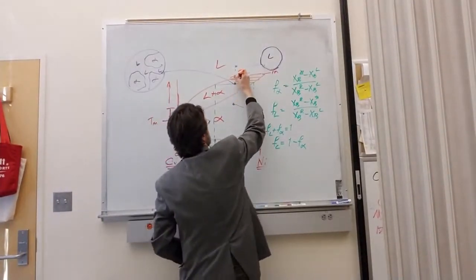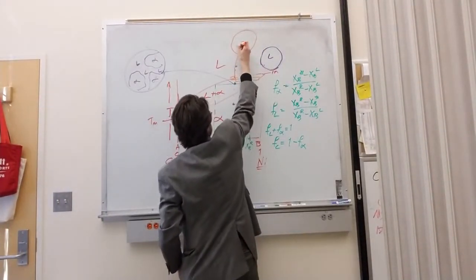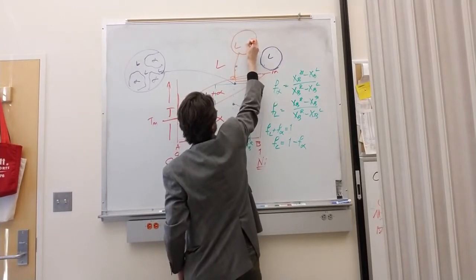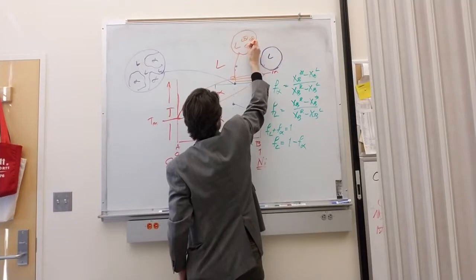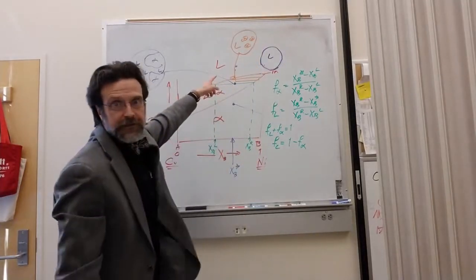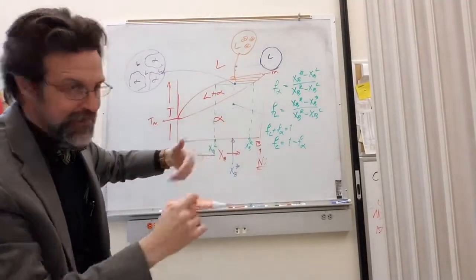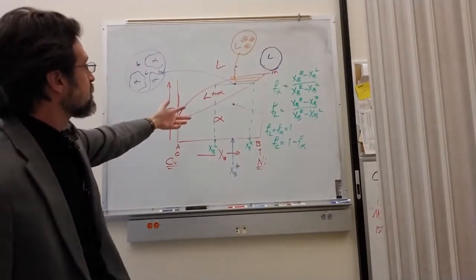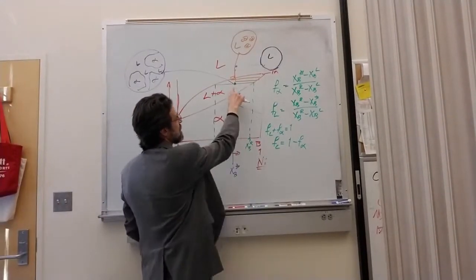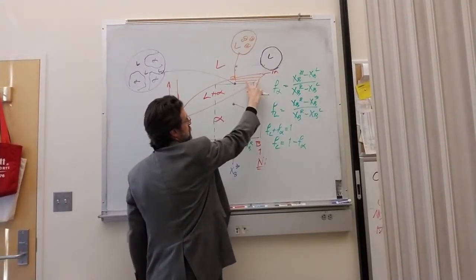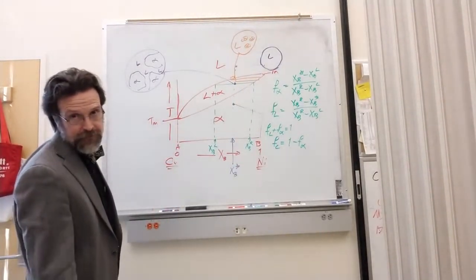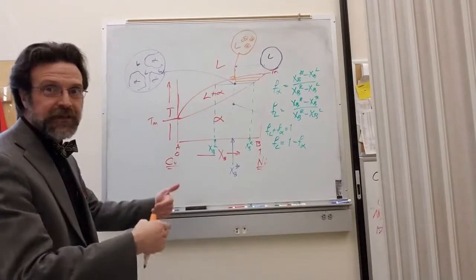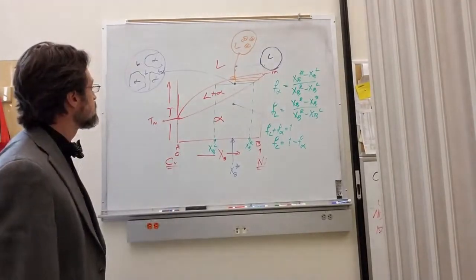So here, looking in the microscope, we're going to have liquid, and then we're going to have a little nucleus of alpha forming, not big. And as a result, we know that the little part divided by the total length should tell us the amount of alpha, or the fraction of alpha.